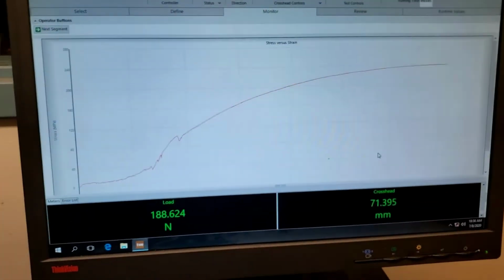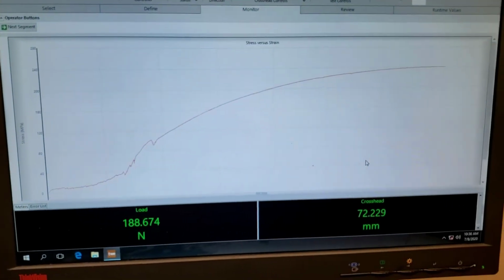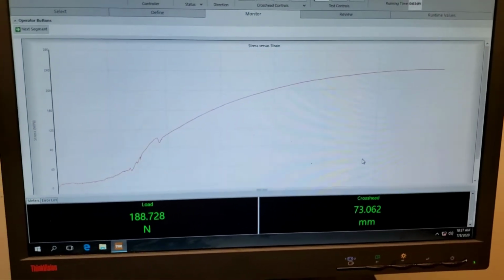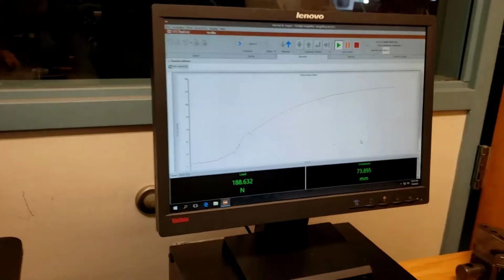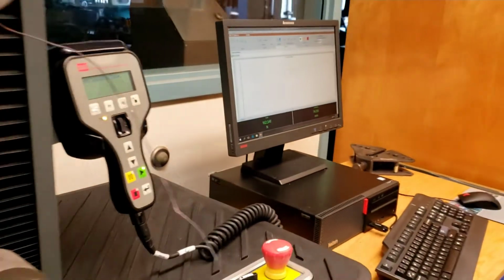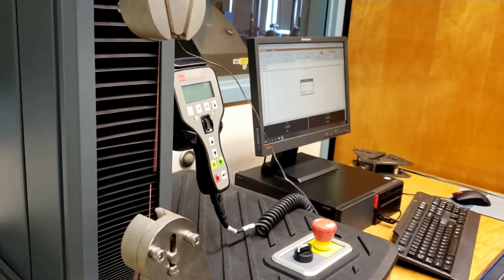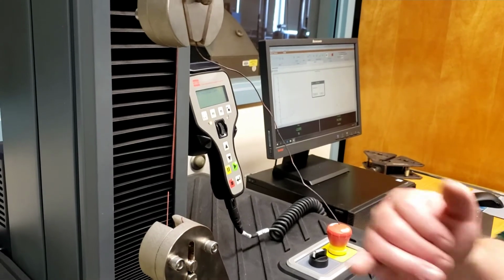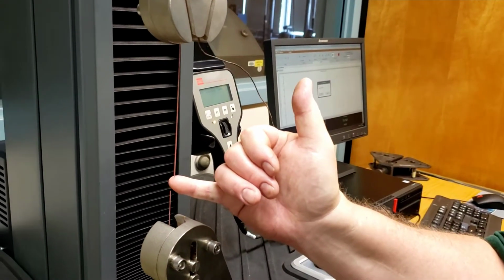You can see that we are at 70 millimeters. 75 millimeters is 3 inches. The wire pulls that much. Copper is very, very ductile. But there it broke. And you can see the breakage here.